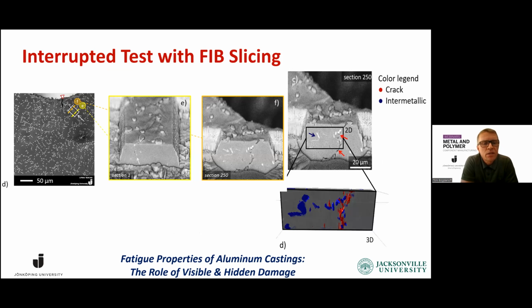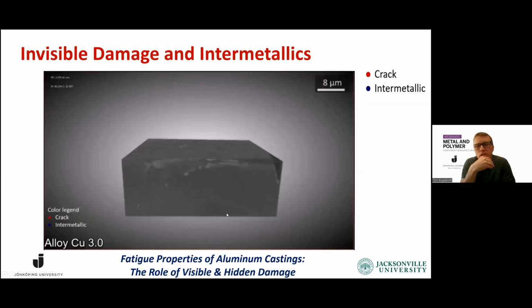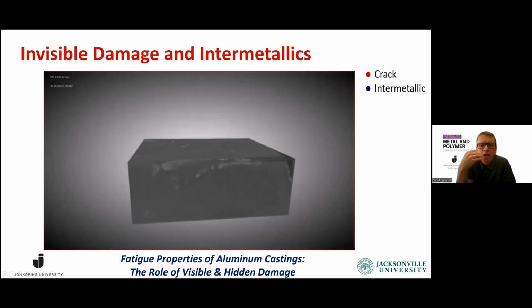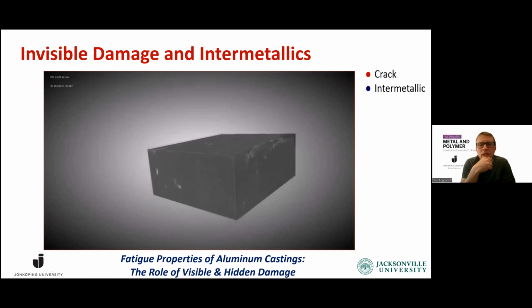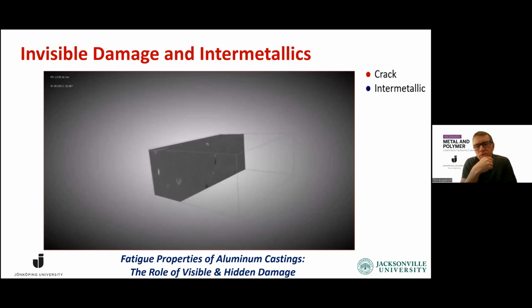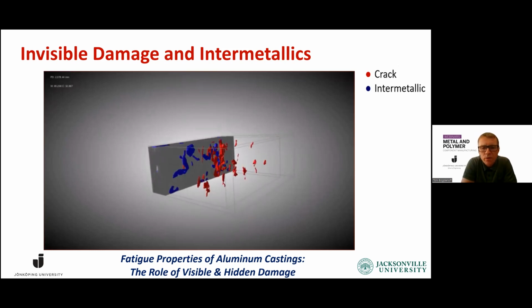So we did a test and then we decided on one area that we should investigate, to see what is happening in front of the propagating crack. So what we do is that we FIB the area around and then we can slice and polish and take pictures, so we get every slice and can see what is happening in front of the crack. So this is the first section and that is the last section, and then we can color everything. So in this case, we see this 250th slice. We have the crack from the beginning, and then we see all of this red. That is the crack that is everywhere in front.